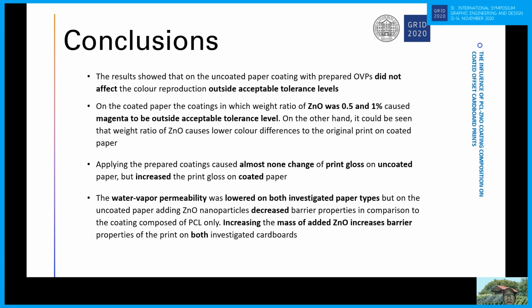To the conclusions, we can see that the only problem really was the coated paper, where magenta got outside the acceptable tolerance level with the 0.5 and 1% mass concentration. We saw that the gloss from the uncoated paper is not really changing, while on the coated paper we increased gloss and water vapor permeability is decreased on coated paper with increasing zinc oxide nanoparticles.